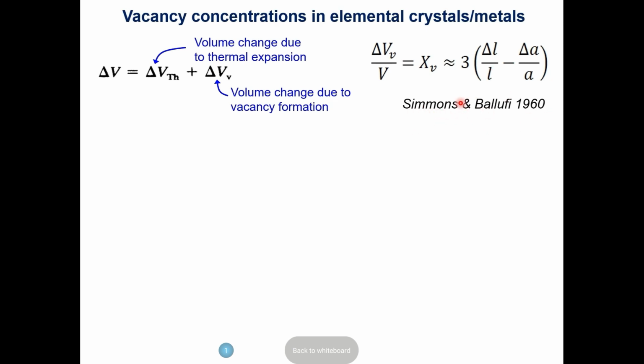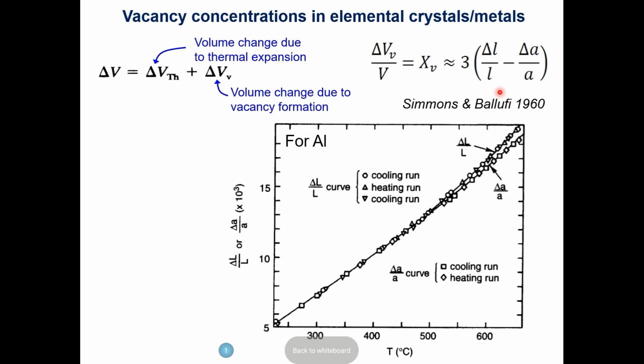This was really proposed by Simmons and Balluffi. By the way, this works very well for elemental solids, but if you want to estimate vacancies in your ceramic sample, using this approximation doesn't work very well. It will give you some rough number, but not more.